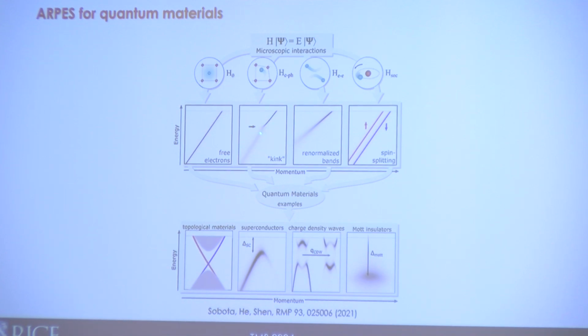Basically, the energy of the kink tells us the energy of the bosonic mode. These could be phonons, magnons, even plasmons. Essentially, you can see that the Fermi velocity, or the slope of the dispersion within the energy, is smaller than the bare band dispersion. And this tells you the strength of the electron-boson coupling.